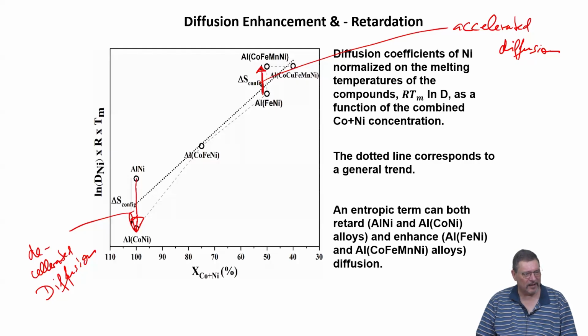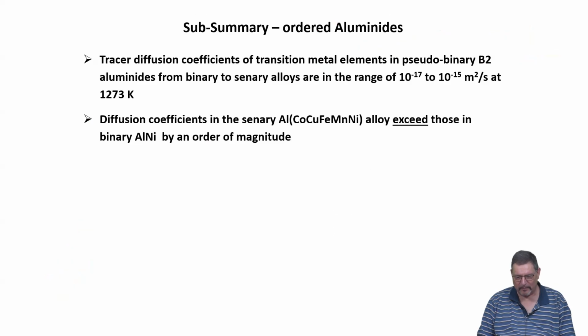So we cannot say configurational entropy of mixing has this and that impact on the diffusion. It is much more subtle, and it much more depends on the specific interactions on the specific lattice site with the specific constituents we are choosing. So this is the unfortunate bottom line of the diffusion measurements. It's not easy and simple. We cannot have a common rule that fits all. We have to really be very specific in terms of how we look at it.